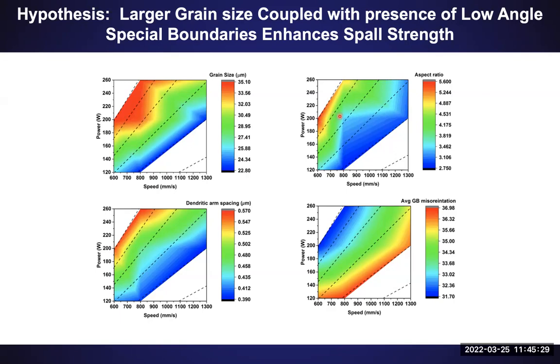about a medium aspect ratio. But the thing that stood out to us is they had very low average grain boundary misorientation. We've done a lot of work that has previously shown that lower angle boundaries tend to resist damage formation as compared to higher angle boundaries. So currently our hypothesis is that this larger grain size coupled with the presence of low angle boundaries is probably helping increase the Spall strength. That is perhaps the reason why the new samples we built are doing better. However, this is something that we're in the process of checking.